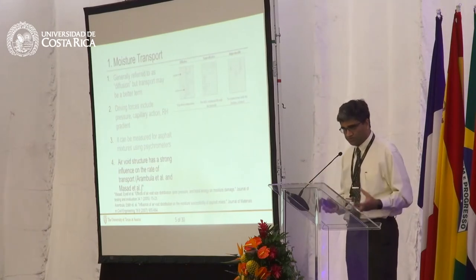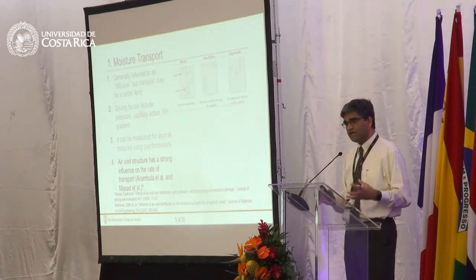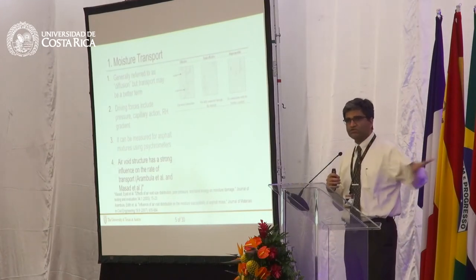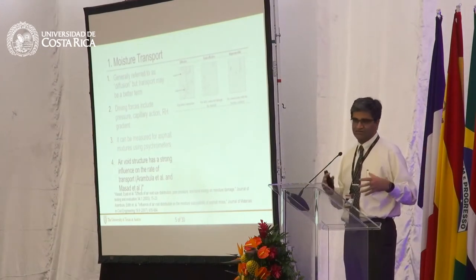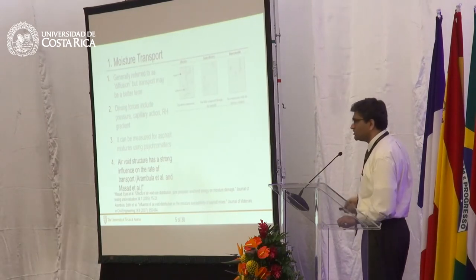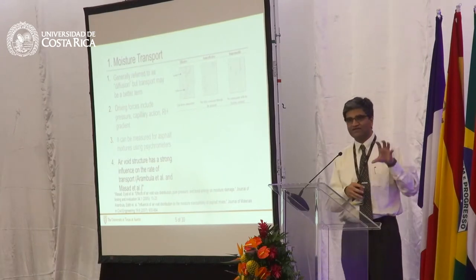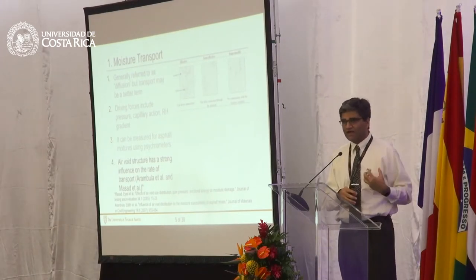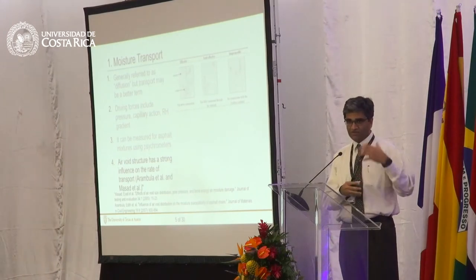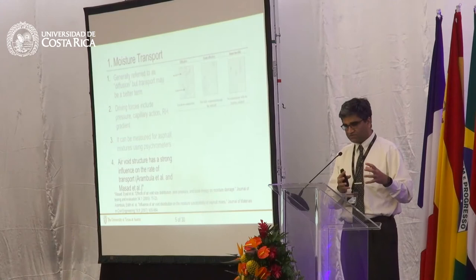If you have a very open structure, like a permeable friction course or open graded friction course, it allows water to go in, but it also allows it to drain out quickly so it doesn't trap the water, and that's fine too. It's this middle place here where you can get into trouble, where the air void structure of your mix is such that water can get into the mix, but it doesn't get out easily. And in that scenario, you have water that gets trapped in, and because of the action of the vehicles, it develops internal pressure, creates erosion, and so on and so forth.